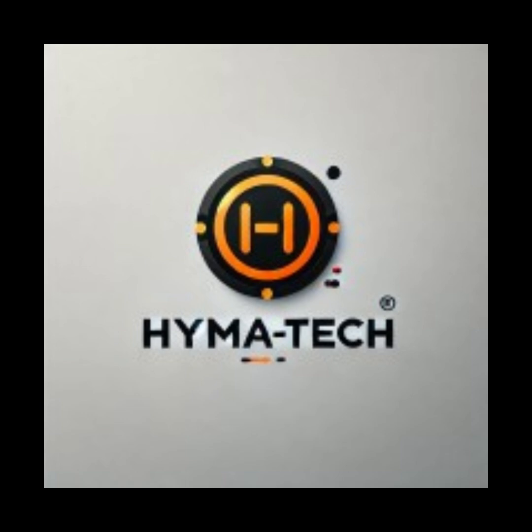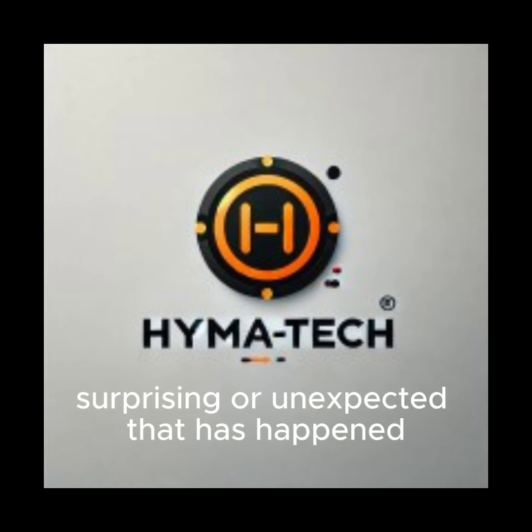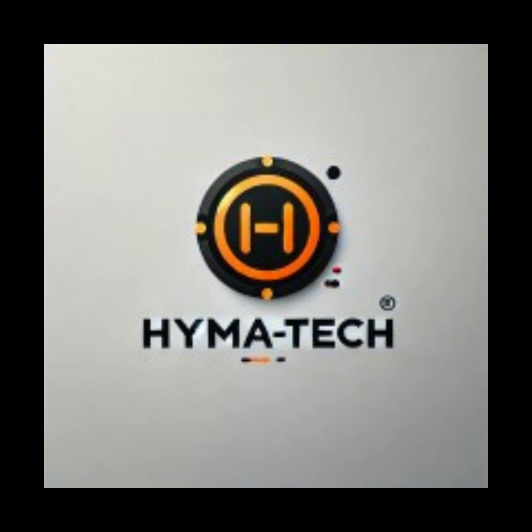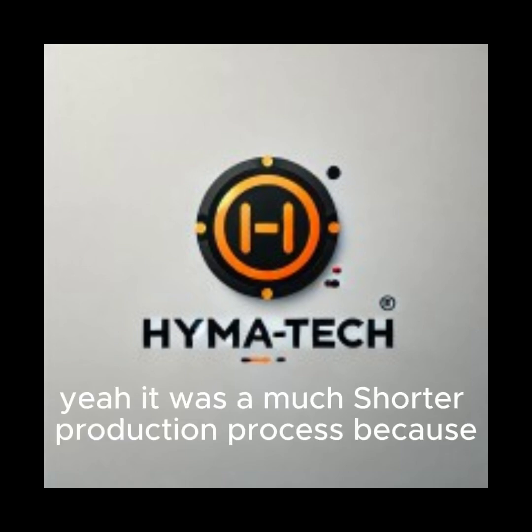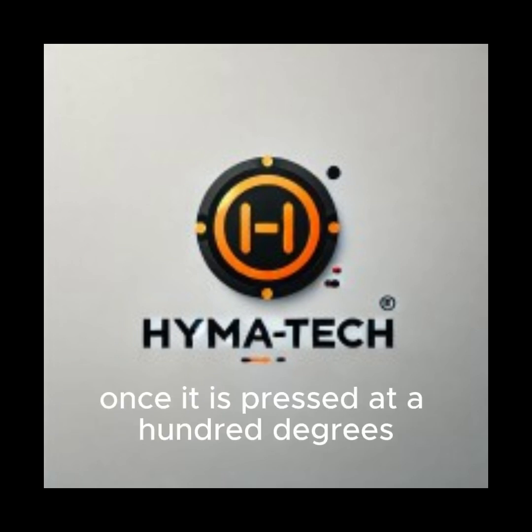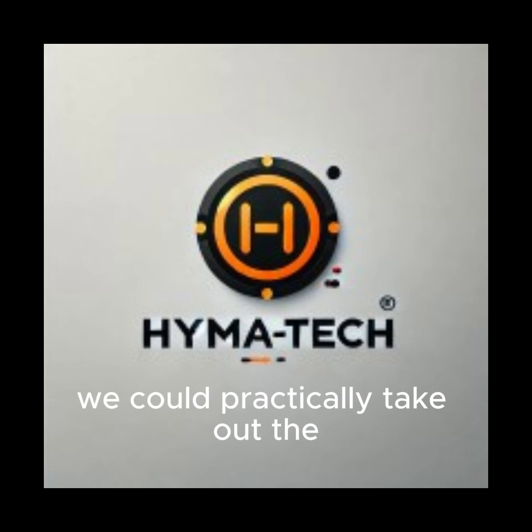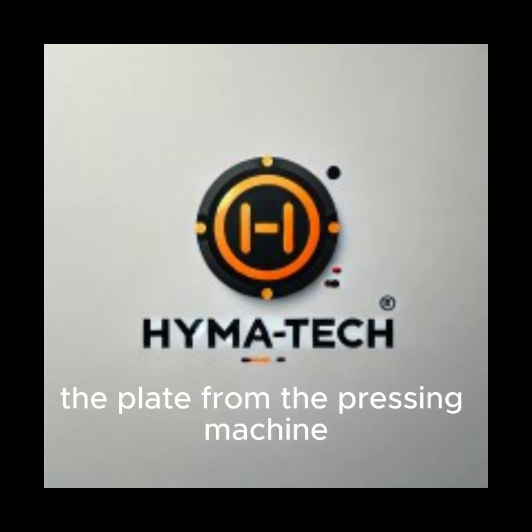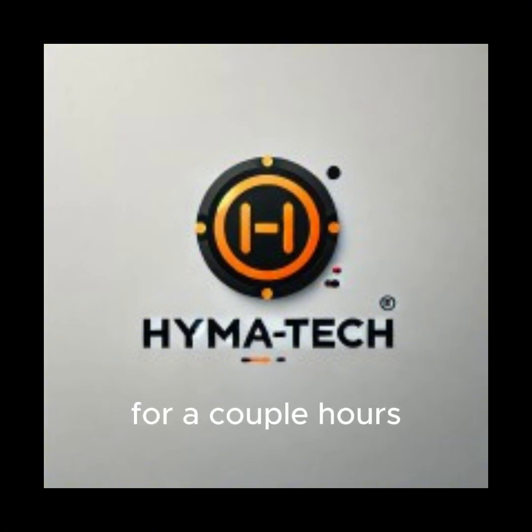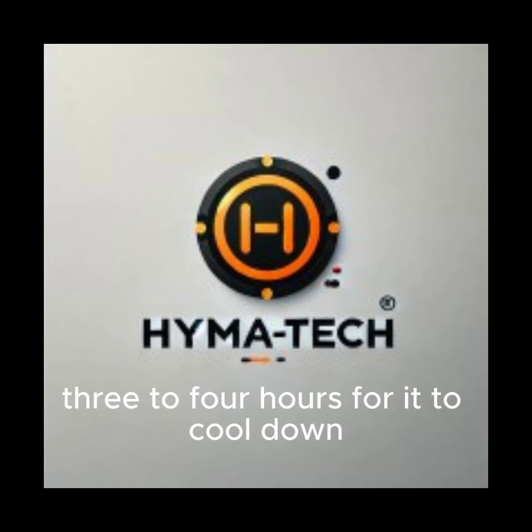All right. Was there anything surprising or unexpected that has happened during the project? Well, we expected that it would be rougher and harder for the material to flow because of the cooler temperature, and the short shot was somewhat expected, but it was a much shorter production process, because once it is pressed at 100 degrees, we could practically take the plate out from the pressing machine really quickly, rather than waiting for a couple hours, 3 to 4 hours, for it to cool down.